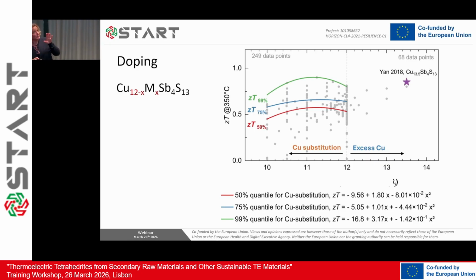So now, again with the meta-analysis of the many papers in the literature, we wanted to understand the doping—how much should we dope. When we plot this graph, here it's copper substitution and here it's copper excess. Apparently from the literature, it's usually good. This is the undoped composition, and the average is somewhere here. Again, look at the dispersion—enormous. But in this case there seems to be a trend that it's good to have excess copper. Of course the data is a bit poor, but there seems to be indication that it's good.